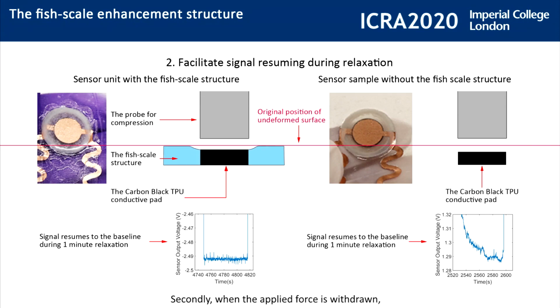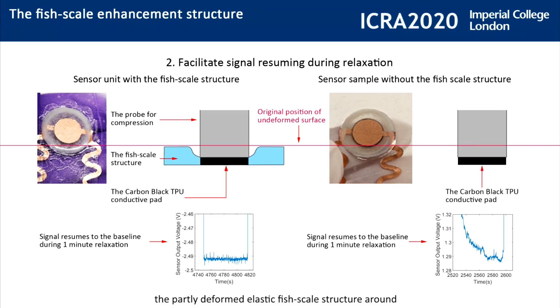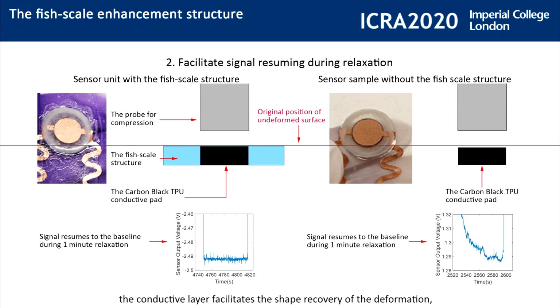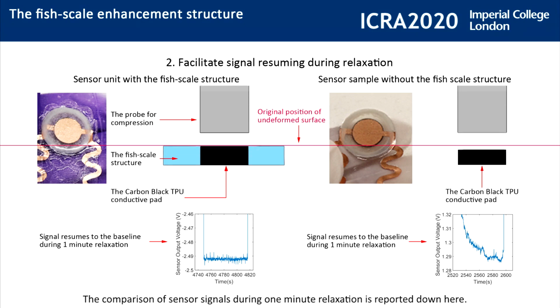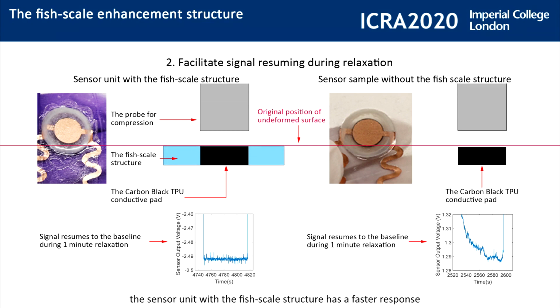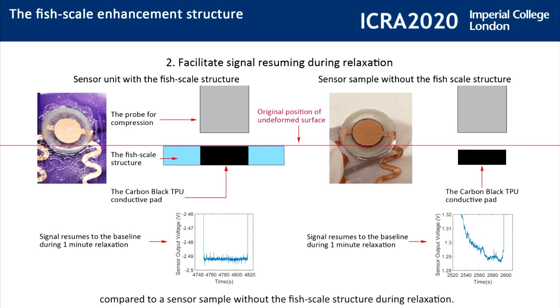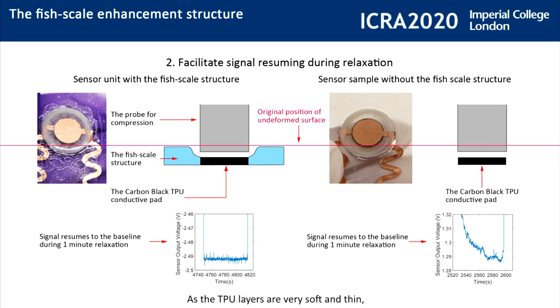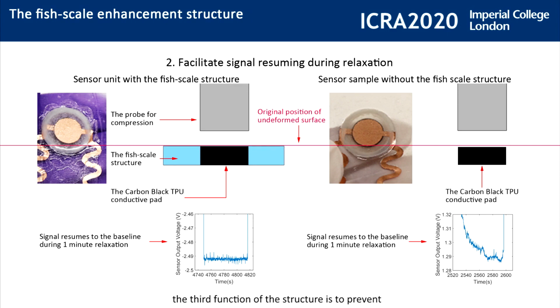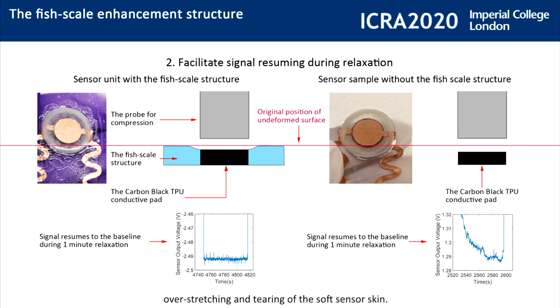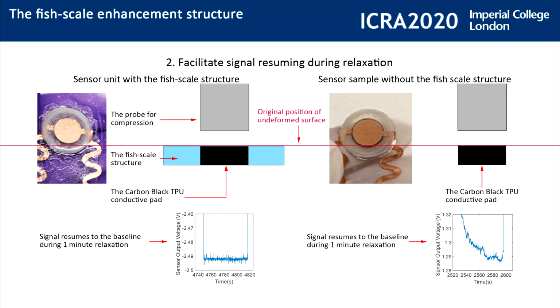Secondly, when the applied force is withdrawn, the partly deformed elastic fish scale structure around the conductive layer facilitates the shape recovery of the deformation, quickening signal restoring to the baseline. The comparison of sensor signals during 1 minute relaxation is reported down here. It can be noted that the sensor unit with the fish scale structure has a faster response compared to a sensor sample without the fish scale structure during relaxation. As the TPU layer is very soft and thin, the third function of the structure is to prevent overstretching and tearing of the softer sensor skin.